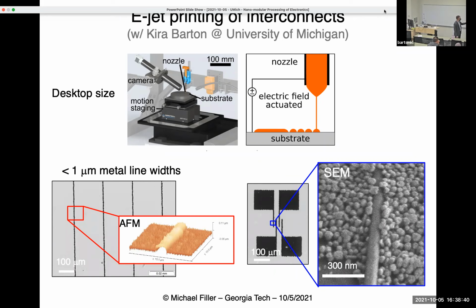And they've already been able to take silver metal lines and get them below 1 micron, which is a really great step forward for the team. And then this shows you a little bit about what they look like when the particles that are the metal wrap around the nanowire that they're printed on top of. So early stages still, but this is where we're going with Dr. Barton's group.